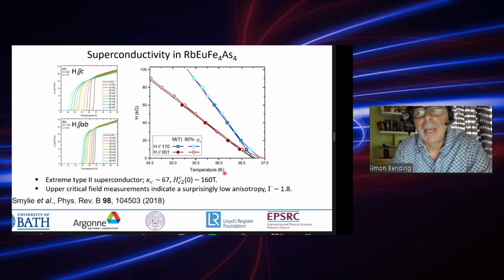The superconducting properties can be extracted really from this plot here. This shows resistivity data as a function of temperature at different applied fields. Here the fields have been applied along the c-axis, perpendicular to the iron arsenide planes, and here they've been applied in plane. And you can see that while there is some anisotropy here, nevertheless, if you calculate the upper critical fields and also the Ginzburg-Landau kappas, you find that these lie in the extreme type 2 superconducting limit.